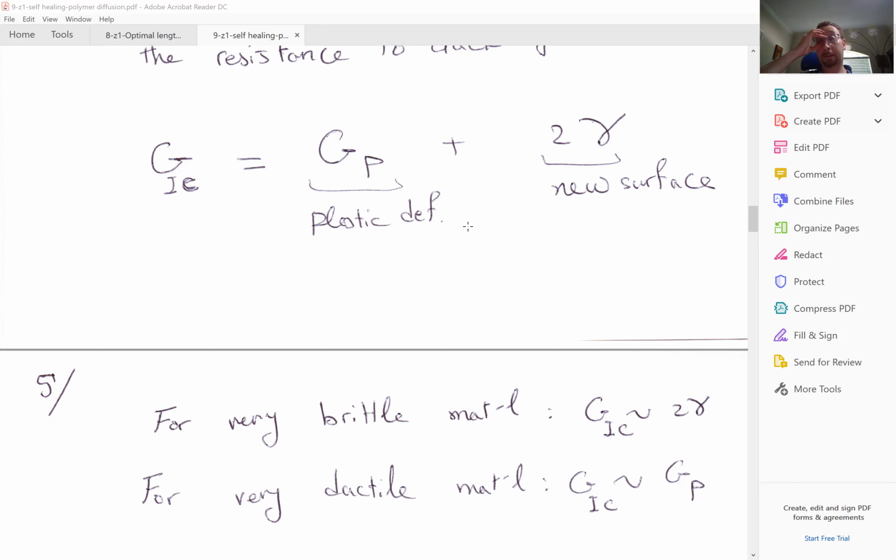the surface energy. Now, as you can imagine, when we have plastic deformations, we need to dissipate more energy because this term is present. So if a material can deform plastically, like metals, many metals, not all metals, with substantial plasticity, then propagating cracks will become a more difficult job. These are energy per unit area, basically. This is what suppresses the crack growth.